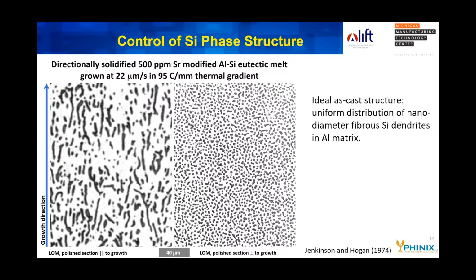This work has been done by Jenkinson and Hogan in 1974. They were also modifying the aluminum silicon eutectic melt, this time with 500 ppm of strontium. And you can see the section parallel to the growth direction and perpendicular to the growth direction. Again, you get this fibrous dendritic growth of silicon, which is black, but with the fiber diameter of about 250 nanometers. This is pretty well what we would see as an ideal microstructure to start with for making a silicon dispersed nanocomposite.